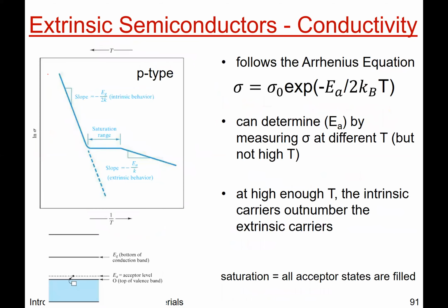Same thing for P-type, you have saturation where all the acceptor states are filled. So that's this range right here where once they're all filled, as you increase temperature, conductivity doesn't change. Okay? And then it goes into intrinsic type behavior. And your book has this, they just have it flipped around. So your book plots the lower x-axis as temperature. And so this plot will just be the mirror image, but it's the same process, just with the x-axis flipped.